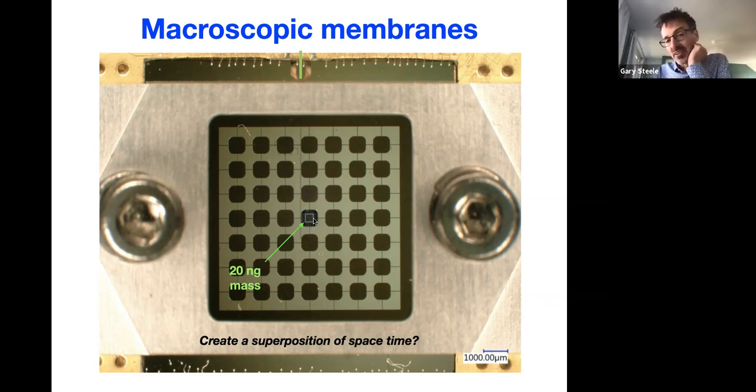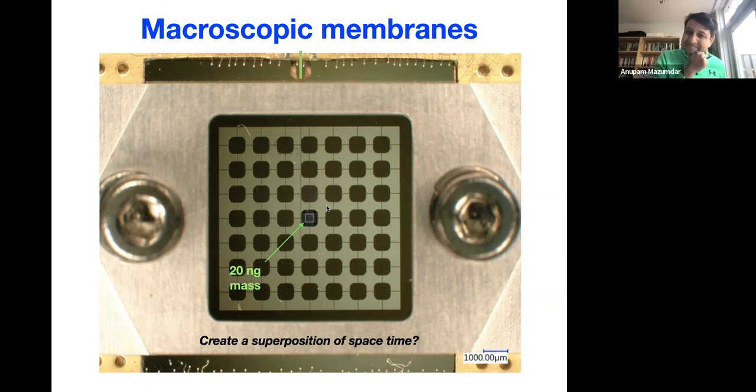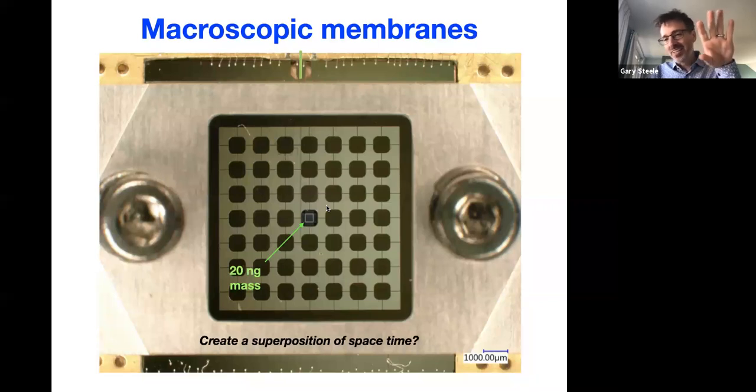And actually, this little membrane, I didn't have time to talk about it, is the mechanical resonator. It's the heavy thing we want to use to try to reach this gravity limit. That one has a tremendous coherence time. The decay time of the one that we measured was 140 seconds, which is a Q factor of 129 million. That's very good. I have a colleague in Copenhagen who at 10 Kelvin showed 1 billion. If we combine our scaling to millikelvin with their result, in principle we should hit something like a 10 billion quality factor. That's very good.